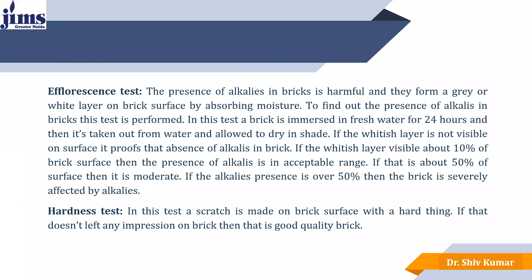Next is the efflorescence test. The presence of alkalis in bricks is harmful — they form grey or whitish layers on the brick surface by absorbing moisture or water. To detect alkalis, the brick is immersed in fresh water for 24 hours, then taken out and allowed to dry. If no whitish layer is visible, it proves absence of alkalis. If the whitish layer covers about 10% of the brick surface, alkali presence is at an acceptable rate. If it is about 50% of the surface, it is moderate, and if it exceeds 50%, the brick is severely affected by alkalis and should not be recommended for construction work.